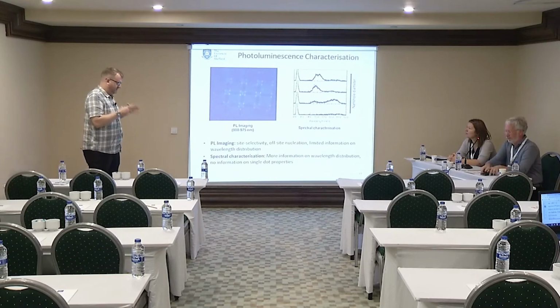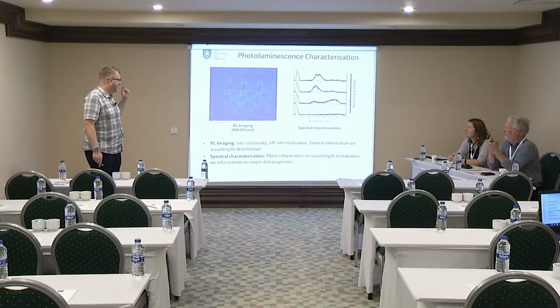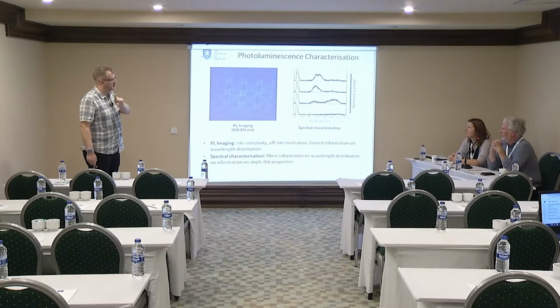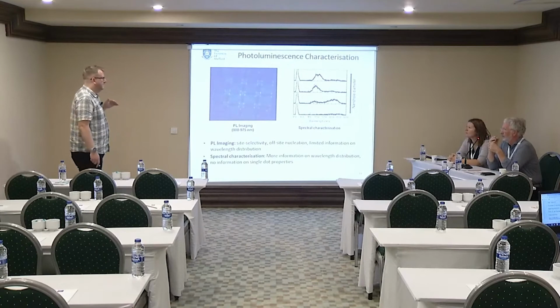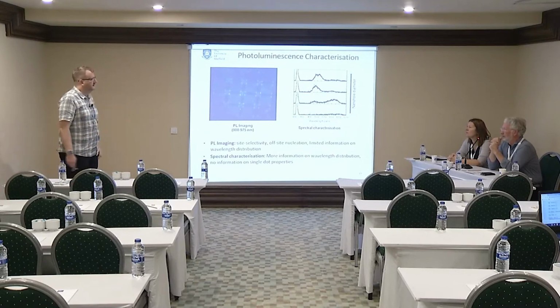Across, it's a quarter of a 3-inch wafer, so it's pretty large. We haven't started to look across all of the patterns to see whether there are edge effects and so on going on. We're not at a temperature that's so hot that we could be desorbing at the edges of the wafers. We kind of check that, but there still could be some variation in the migration length.